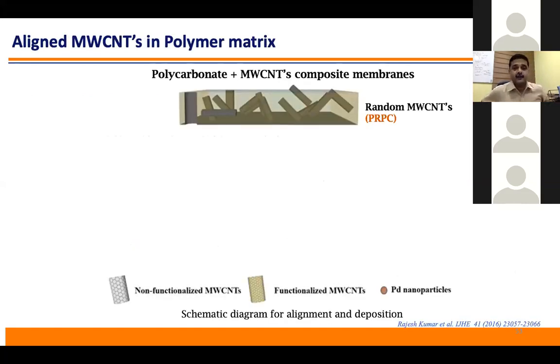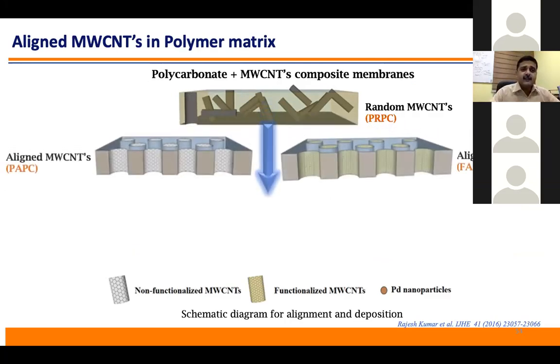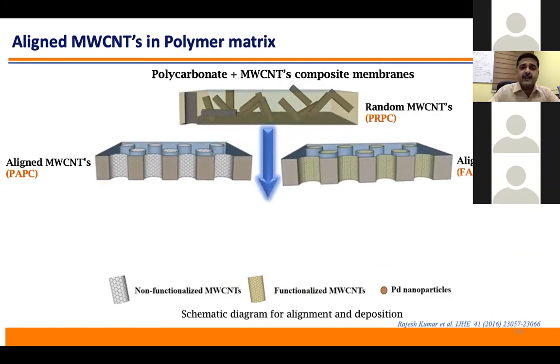Maybe in the last 5 or 10 minutes, I will show you another example of a composite membrane that we made in our lab. We used multi-wall carbon nanotubes, and then we mixed them in our solution of this polymer. This is a polycarbonate polymer, and this is the MWCNT combination. What we did, this is random multi-wall carbon nanotubes, and once the solvent is evaporated, we can use this membrane for some gas separation application.